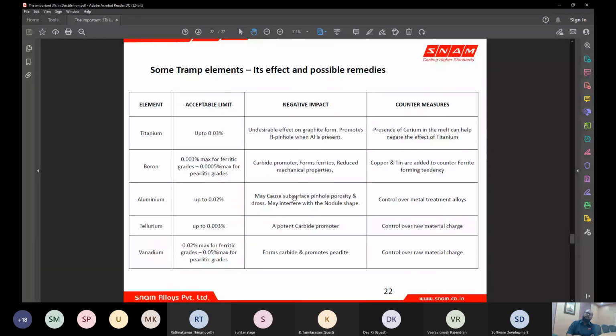What does boron do? Boron is a carbide promoter, and sometimes it forms packs of ferrite, like remote locations, and it can reduce or alter your mechanical properties. So you can avoid boron by finding its source and then controlling it, or you can control your ferrite forming tendency due to boron by adding copper and tin, or ensuring good pearlite promoting elements at a given level. Aluminium, as we know, is a nucleating element.